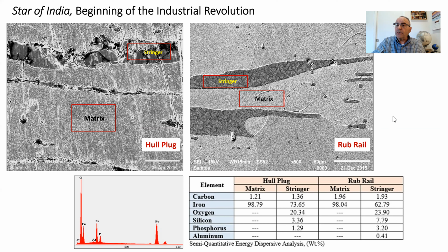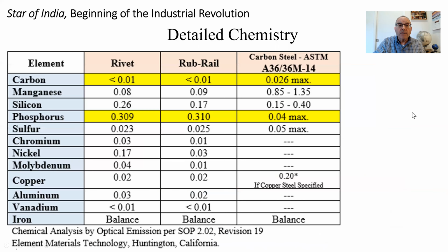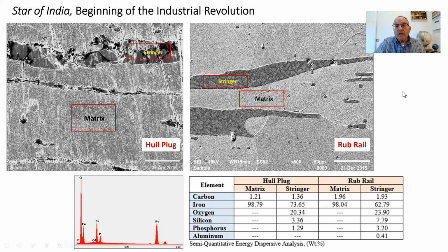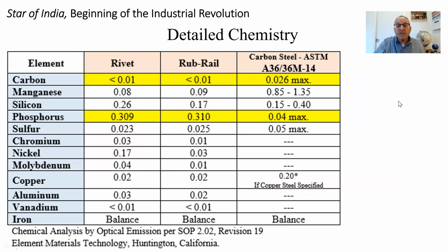So the next thing we did is we took this sample, the rub rail and the rivet, and we took them to a laboratory that did a detailed analysis. And this detailed analysis was what we call an optical emission spectrometry. So it's very detailed analysis, gives us real good quantities. And I put the chemistries in here along with the standards of steel for a low carbon steel that we have today called A36 carbon steel, which is a low carbon steel. So a 0.026 max carbon.